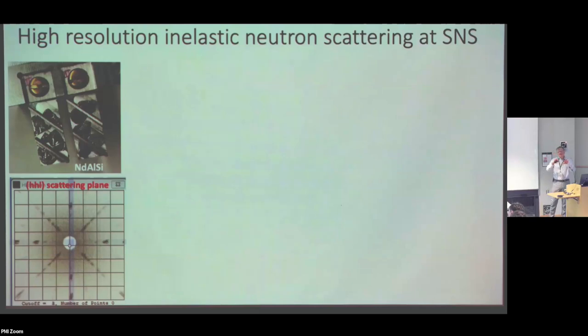Okay, so then we thought we'd take another step and try to actually determine the full nature of the magnetic interactions. Not only observe the wave vector, but really see how strong are the interactions, what's their range, to really make contact with the theoretical work. And so that brought us to inelastic neutron scattering experiments. So actually using the exact same instrument that I talked about yesterday when we were working with this supersolid phase, it's a very high resolution spectrometer called CNCS at SNS. I just wanted to show a couple of pictures of some of the practical stuff, which is what we actually do, and really getting this right is how you can draw some physics out of it.